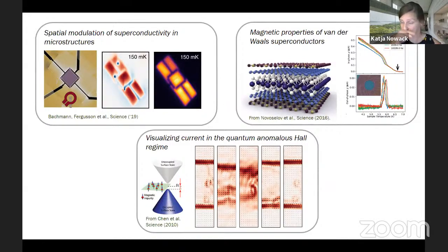So once sigma XX becomes non-zero or substantial, we see a lot of heating effects, we think. Other than saying that we see strong heating effects, we can't say much yet. If you look at simple models of heating for finite sigma XX, it might well be that the electron system heats up not just a subtle amount, but all the way to a few Kelvin. But we are not quite sure why that causes the strong signals that we see. Maybe the magnetization itself ever so slightly changes, but that's an aspect we're still very puzzled about. The only thing we do know is that they're related to strong heating effects.